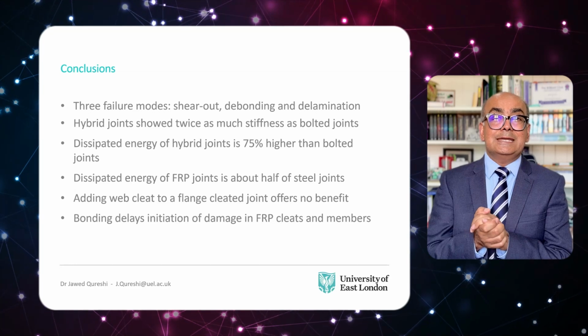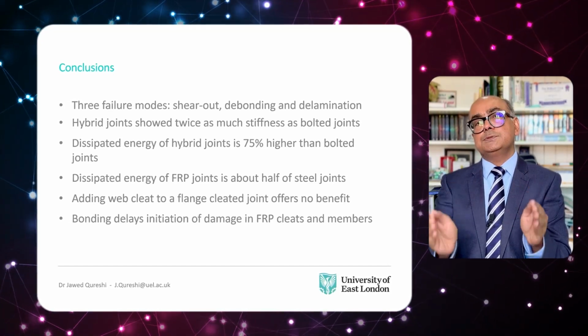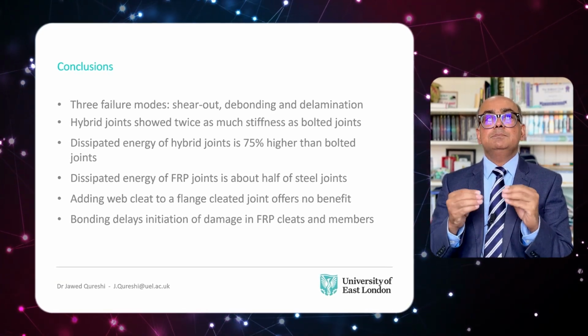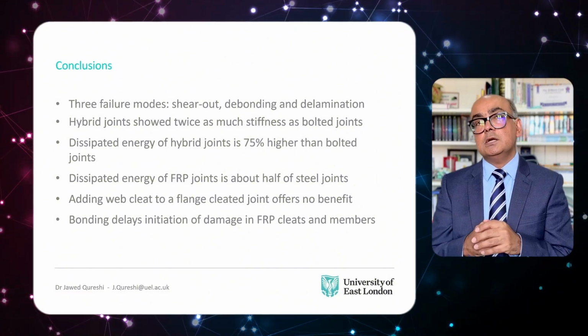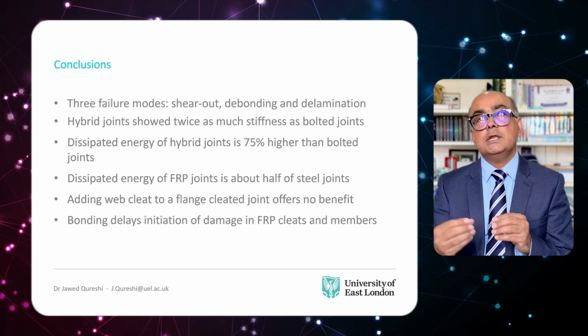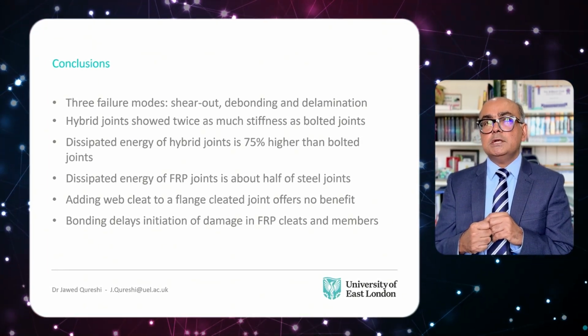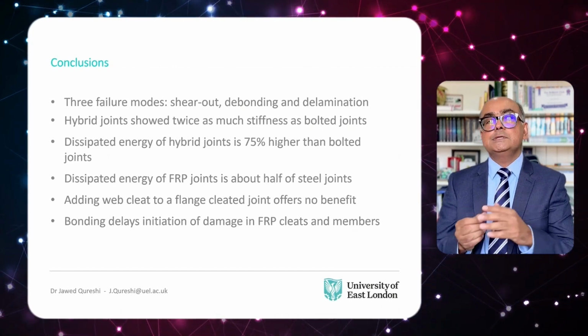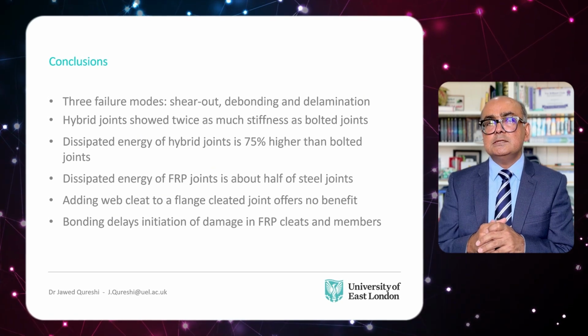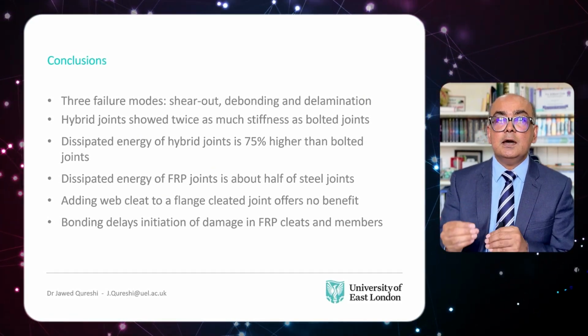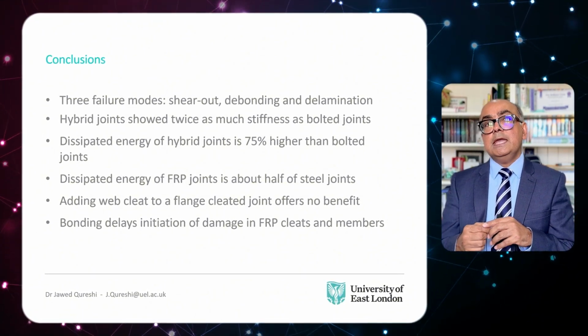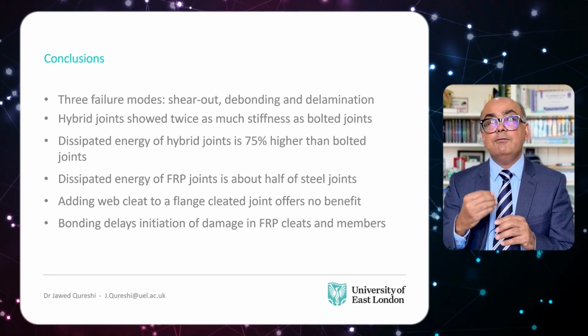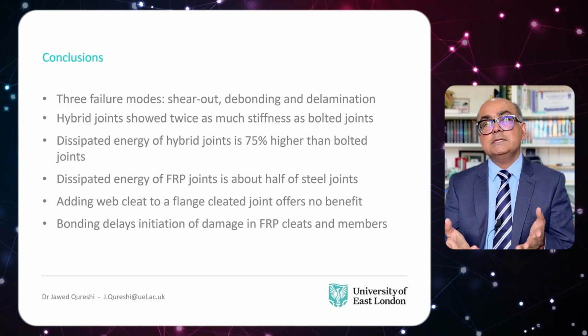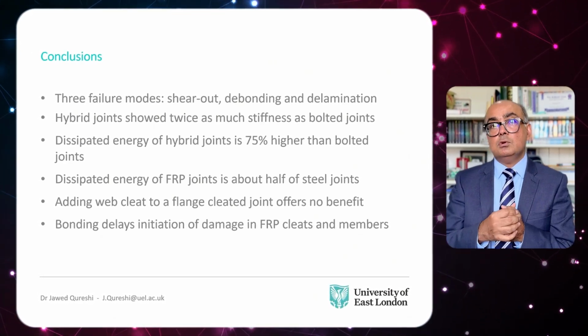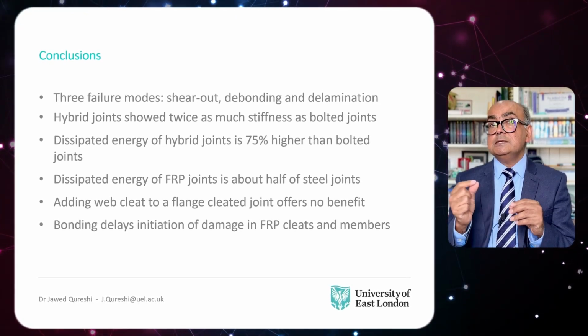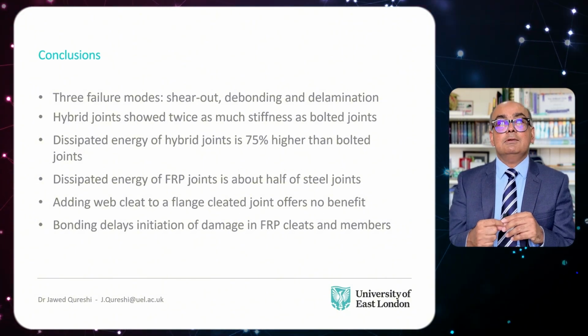Now I'm in a position to conclude the work. There were three main failure modes observed in this research: shear out failure of the beam's bolted zone, adhesive debonding with shear out failure, and delamination cracking at the root radius of FRP cleats. Hybrid joints were much stiffer than bolted only joints. Accumulated dissipated energy of hybrid joints is about 75% higher than companion bolted joints. Energy of FRP cleated joints is about half the steel cleated joints. Web and flange cleated joints compared with flange only cleated joints showed no difference in results. Adhesive bonding delayed the initiation of cracking.